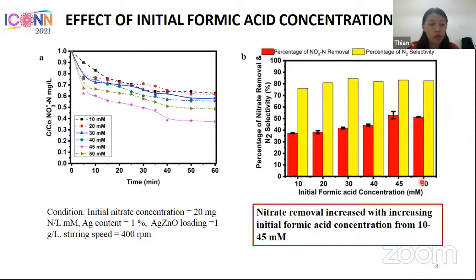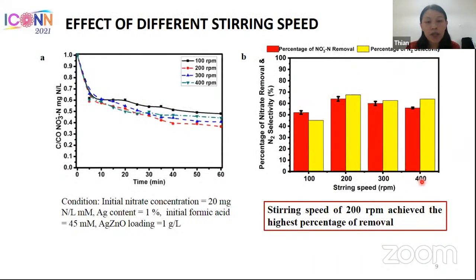increment in removal. Then the next parameter that we studied is the effect of different stirring speeds. So if you can see here, from 100 RPM at lower stirring speed, and as we increase to 200 RPM, we observe an increase in the percentage of nitrate removal, but beyond that, again, it is reducing. So at a lower stirring speed, we observe there is a stagnation and there is a sedimentation of the photocatalyst, but it improves. So as we increase the stirring speed, it improves the percentage of removal.